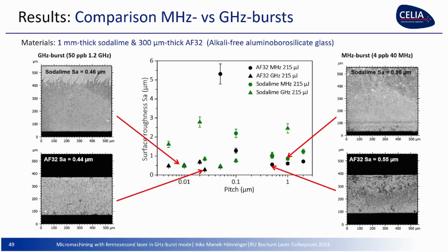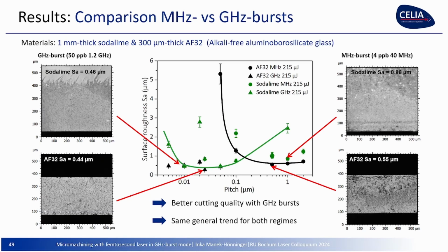However, you see some sleek part here, so maybe the energy was not enough. I will come to that later. So we have a better cutting quality with the gigahertz burst, and we have the same general trend for both regimes. And what you can see is, if you lower the pitch, the successive pre-cutting, the distance between two pre-cutting vessel holes that I showed to you.